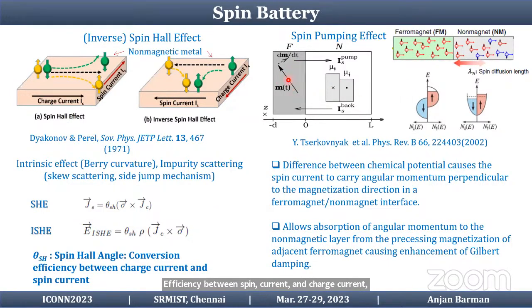Here, if you have a ferromagnet and adjacent to it a non-magnet, then the precessing spin causes a spin angular momentum gradient and a spin accumulation at the interface of the ferromagnet and non-magnet. Due to the difference in spin chemical potential of up and down spin, they will flow into the non-magnet, and there will be a net flow of spin current into the non-magnet, which will be dissipated there, and the damping increases because the spin angular momentum is lost from the ferromagnetic layer.